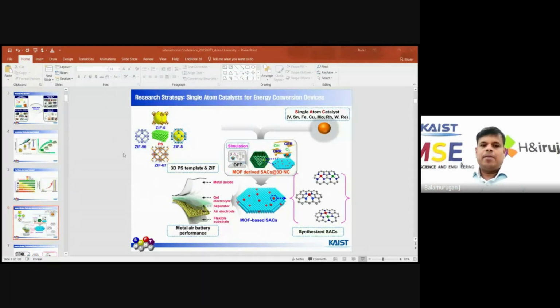So in our case, we fabricated numerous zinc-based organic frameworks, like MOF frameworks. Why do we especially choose MOF frameworks rather than other 2D materials like graphene? Because MOF-based material has a high surface area and high porosity compared to 2D materials like graphene. When we use graphene-based material, restacking effects happen, therefore the surface area is reduced. The reduced surface area may reduce performance, because the restacked material cannot be involved in the electrochemical performance. Therefore graphene-based material may have reduced electrochemical performance compared to MOF-based materials.